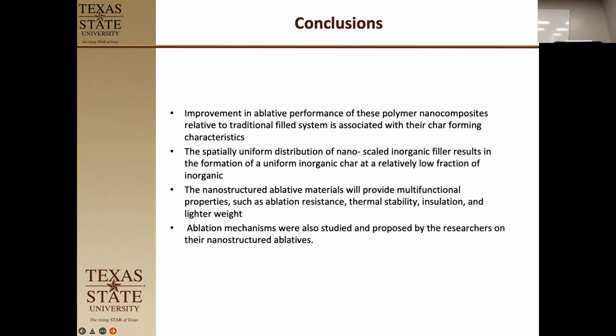The ablative materials had multifunctional properties because it decreased thermal conductivity, it increased the insulation ability, and it made it slightly lighter weight than the carbon stuff, and it also improved resistance. So that was a win-win, right? And the ablation mechanisms were studied in those nano structure ablators. So the idea here is that just with that one system of 5 weight %, they saw improvements in properties that led them saying, okay, so their next paper is going to do 7.5, 10. See how much they can get in there.